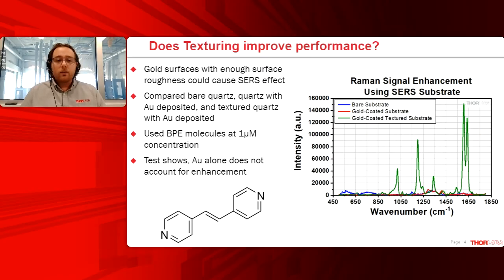And one thing I would like to mention is that throughout the rest of this talk, we used BPE molecules for a lot of our testing. These are just a common molecule used for Raman standardization testing. And what you're seeing in these plots here, these peaks, they're actually associated with the chemical bonds in this BPE molecule. So for example, some of these peaks are associated with these nitrogen rings breathing in and out or vibrating. Some of them are associated with the central point vibrating in different ways.